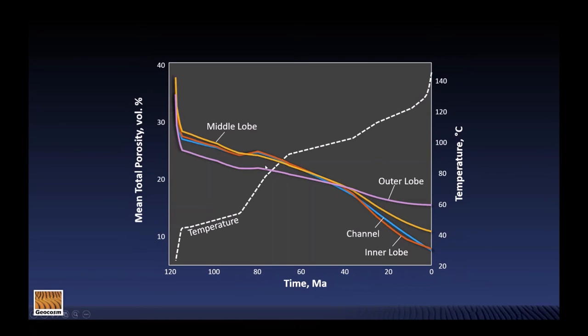Now, through time, what we see is that we have this general decline in total porosity for all the facies, but eventually there's a crossover point where the rate of porosity loss here in the outer lobe is quite a bit less than in these other facies. Now, this occurred about 40 million years ago, and we can see that the temperature at that time was roughly 100 degrees C, which is just when silicate reactions began to take place. So as you might have guessed, most of the porosity loss in this part of the burial history is resulting from quartz cementation. So let's take a look at the quartz cement results for these basins.